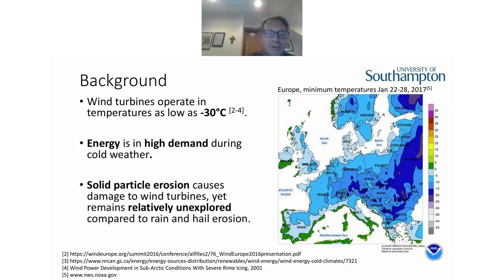Just to reassure you of the need for this, this is a map of temperature, and you can get down to minus 30 in parts of Europe, and obviously when it's cold, the energy demand goes up. So wind turbines, wherever they're situated, need to extract energy. The main damage is caused by liquid droplet impingement. That is difficult to do at low temperature experimentally, so we switched to a solid particle erosion facility, which looked pretty unexplored at the time. It is relevant because there are particles, hail in particular, that might hit the blade. They are quite different, though: the erosion performance against liquid droplets will be slightly different to solid particles.